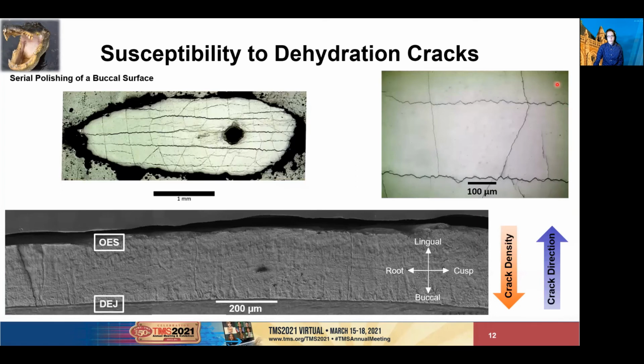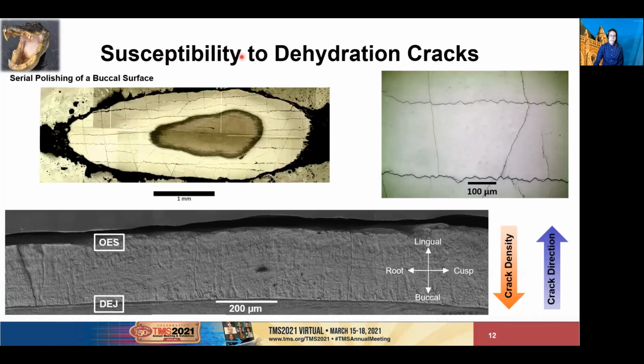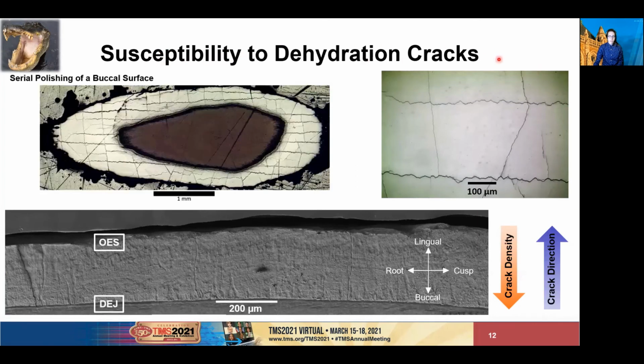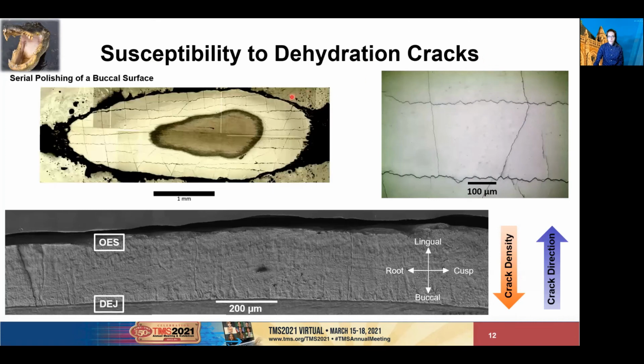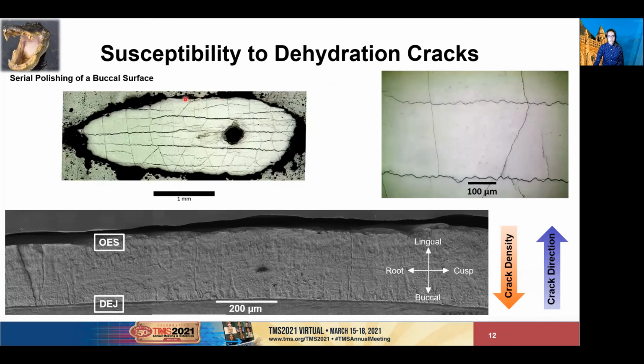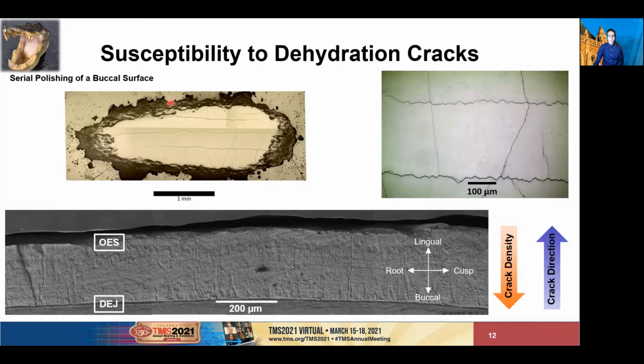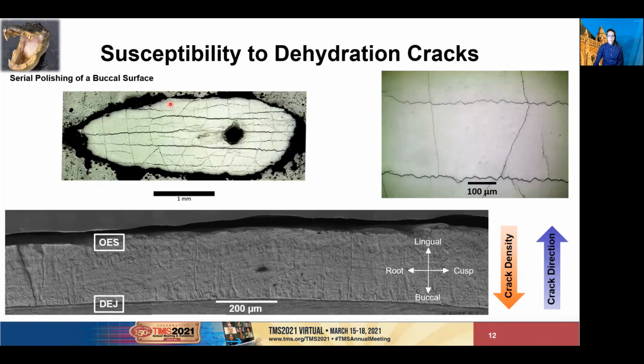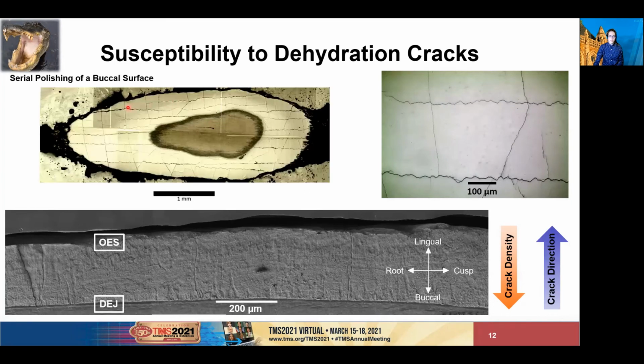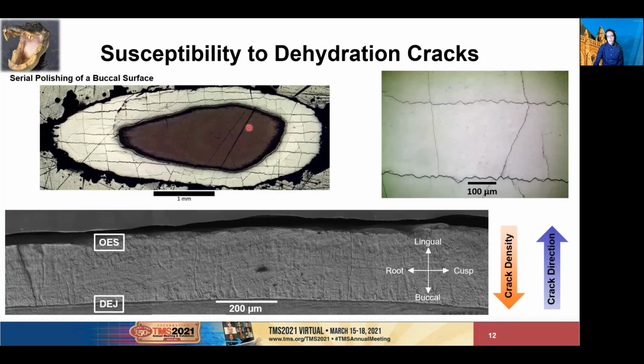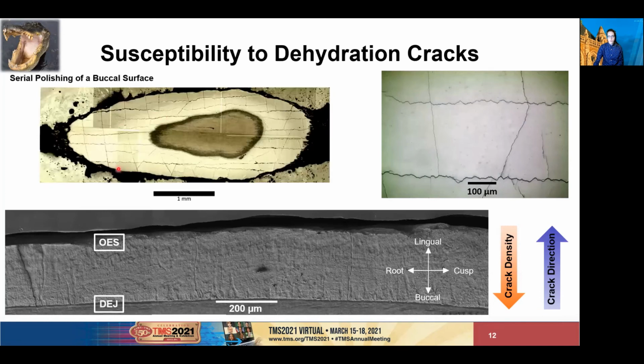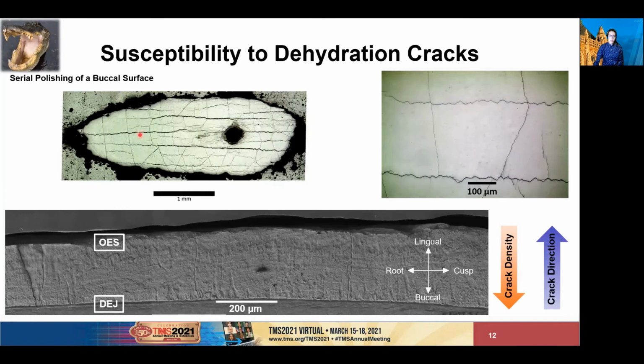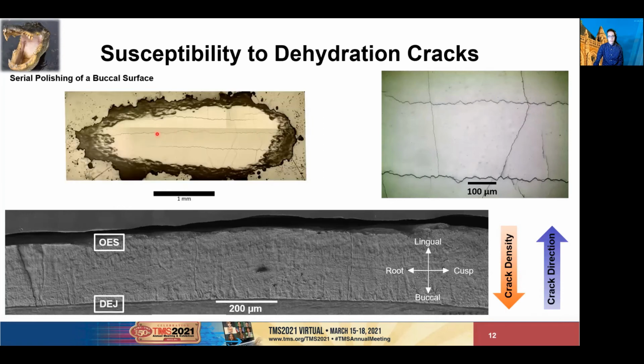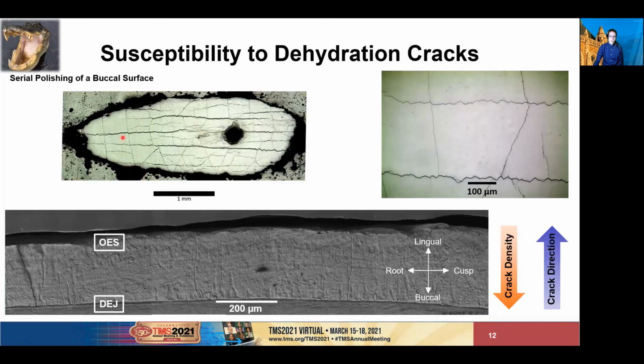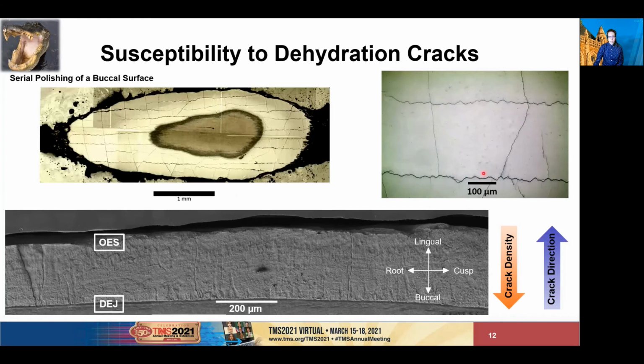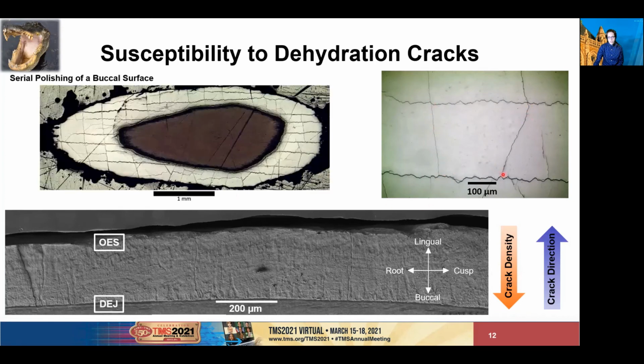The final preliminary investigation I would like to share with you all is the susceptibility of alligator enamel to dehydration cracking. This GIF shows the buccal surface of the tooth looking towards the interior dentin, with a delta Z of about 30 microns between each imaged layer. This region in the middle is the dentin, but more interesting is the extensive network of cracks that form throughout the enamel, both in the long direction of the tooth from root to cusp and circumferentially. The result is these cells of enamel separated by cracks. And these cracks are quite deep.